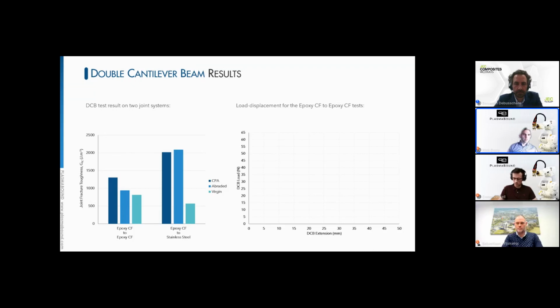Additionally, and to give you a little bit more clarity on the epoxy to epoxy bonds that occurred on the left-hand side, these are the load displacement curves that were generated, a sample of them, during testing. The untreated gave a very large variance in the max load that was achievable. And abrasion, which followed, gets a significant improvement in these groups, but still demonstrated a catastrophic failure.